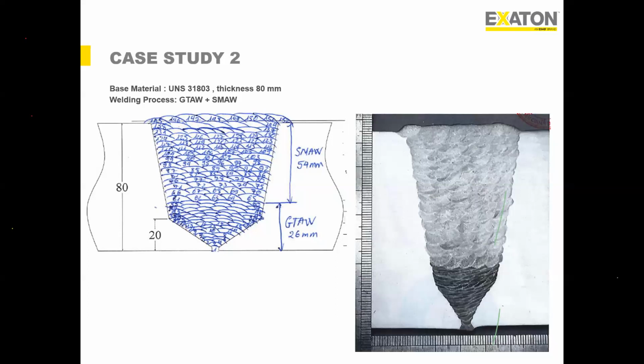So we tried to start the welding, but we found that the grinding disc or grinding wheel was absolutely impossible to get in there. So what we did was weld another 6 millimeter, which makes 26, and the remaining 54 millimeter with the SMAW process, so that the grinding disc could also go inside. This is a lesson learned: when we design a welding process, we also have to take care of parameters like whether the welder has enough access to weld on the root side, or whether the grinding disc has enough access, because we might need to do grinding. So this is the thing.